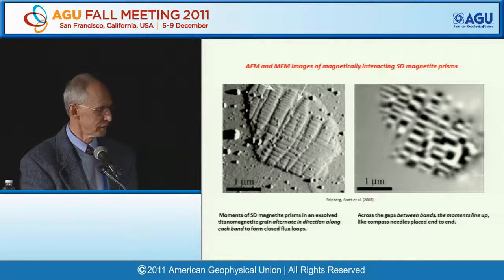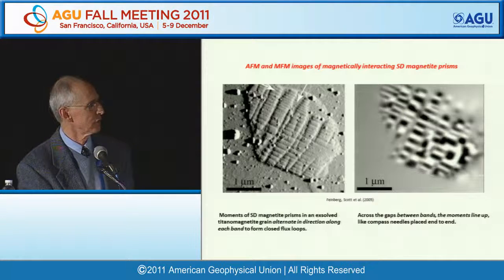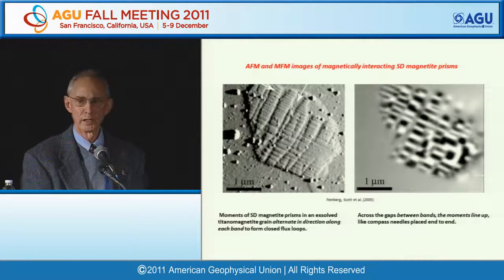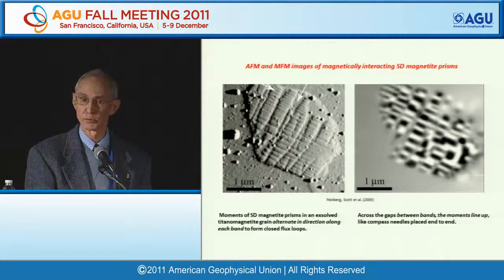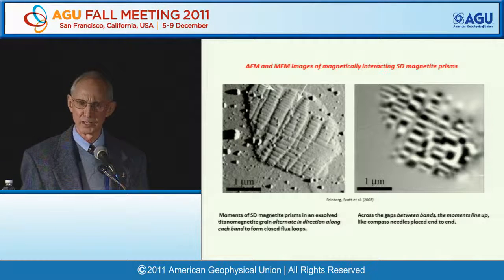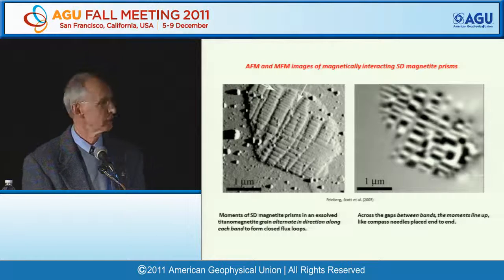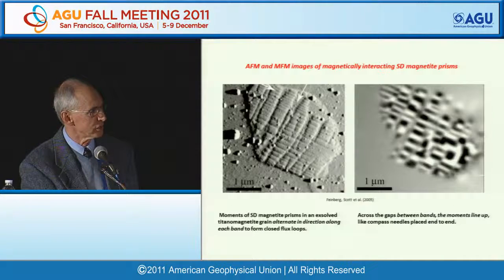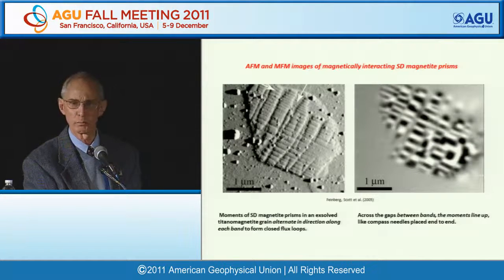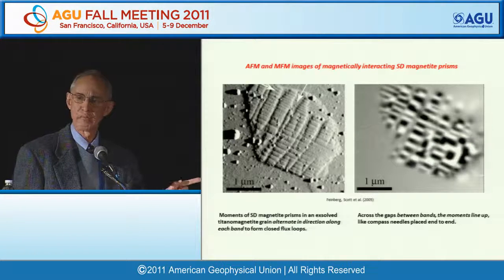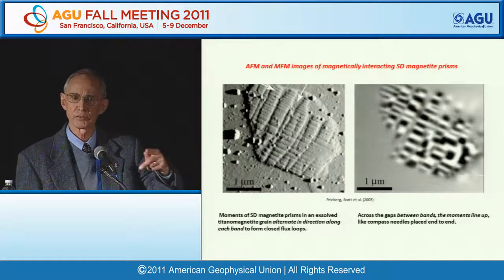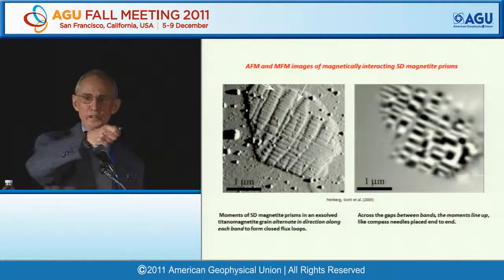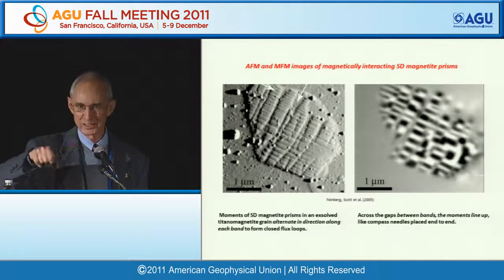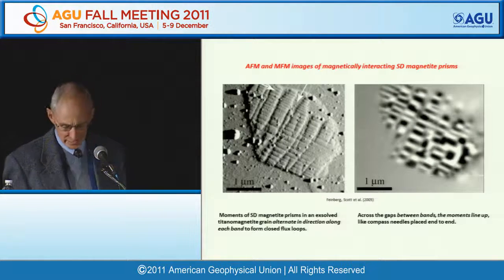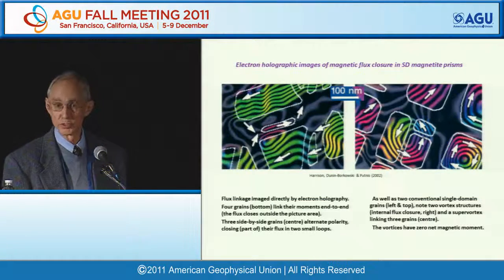Well, this effect of interacting neighbors has been shown beautifully in AFM and MFM images taken by Josh Feinberg and Gary Scott and colleagues. These are not separate domains, but along this band here we have neighboring single domain magnetite prisms, which are separated from each other by non-magnetic or practically non-magnetic ulvospinel. And in the MFM image, you can see that the colors go white, black, white, black, white, black, white, black. These are left magnetization, right magnetization, left, right, left, right. They alternate. You can weave your way through them in a flux pattern. They like to close their flux. The net moment, unfortunately, is very small.